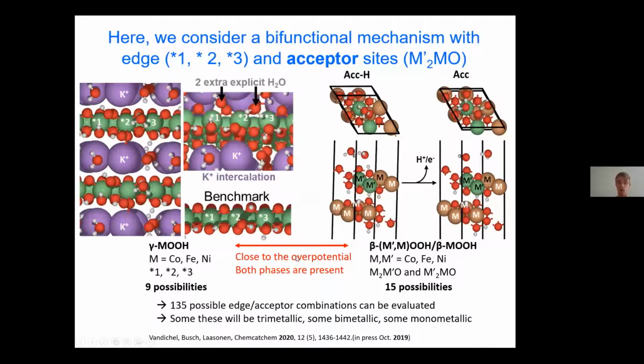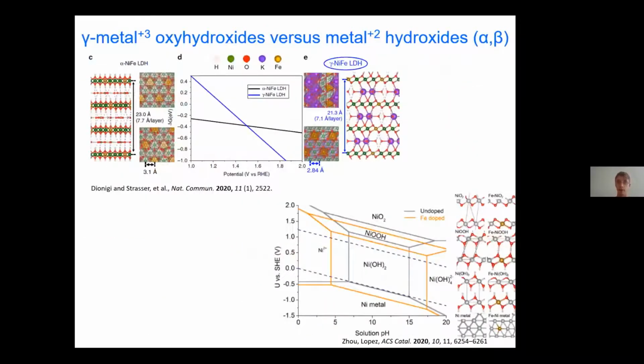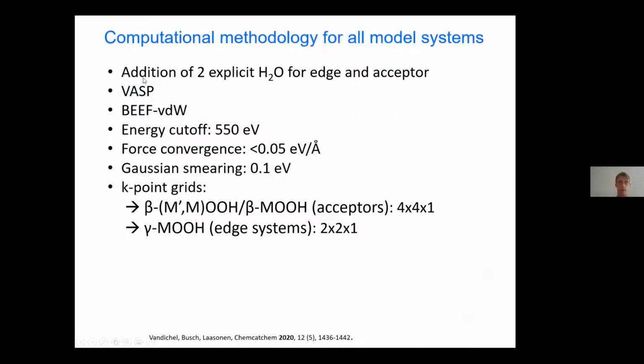And actually, close to the experimental overpotential, so when the OER process is happening, these two phases of metal oxyhydroxides are both present. Even recent computational studies indicate that. So we see the hydroxides as active catalysts. So how do we describe that computationally? Or how do we calculate the different states? I calculated it in VASP with the BEEF-vdW functional. And these are then some computational parameters that we set.